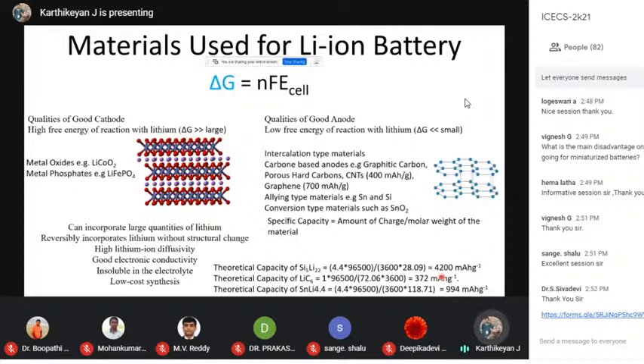So if you have more and more theoretical capacity, you are going to have more and more charge stored in it. One such interesting material is silicon. Yes, silicon has the highest theoretical capacity. For the Zintl phase Si5Li22, the capacity is 4000 milliampere hour per gram. So if you have 1 gram of this material, you can deliver a current of 4 amperes for an hour.